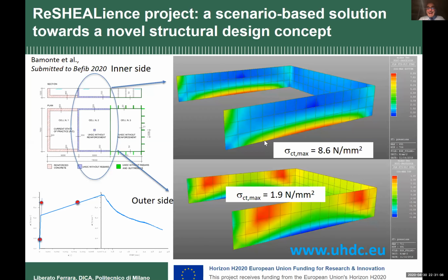But if we compare this level of stress with the constitutive curve of this material, we can see that we are at these 2 dots. 2 megapascals is still in the elastic range. And 9 megapascals, if you continue with the elastic initial stiffness, you would go out of the constitutive relationship.